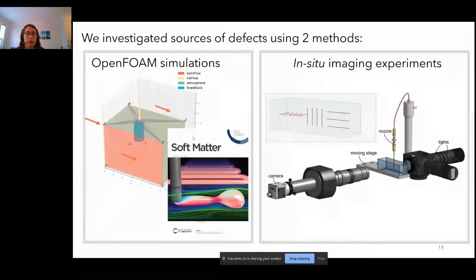We also used in situ imaging experiments. So again, we have a static nozzle and a moving bath, but this time we have a camera looking at the tip of the nozzle so that we can see what's happening as we're printing. And then once the print is over, we can remove the nozzle and go back and take images of our print. So for these experiments, we printed straight lines where we looked at the lines head-on to identify their cross-sectional shape and printed them out from the side to look at their lengths.